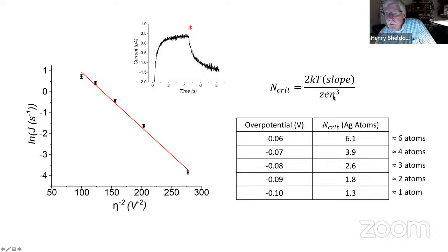You don't like parameters raised to the 3rd power in experiments because that always introduces a lot of error. But this overpotential is just the electrode potential. We can measure that within a millivolt or much better, so there's very little error here. And in these constants, there's no error whatsoever. So here's the set of results. These are the overpotentials that we're making the measurements at, corresponding to these 5 points here. Using this equation, you calculate the number of silver atoms in the stable, critical size nucleus. And you see at low overpotential, we're getting 6.1.